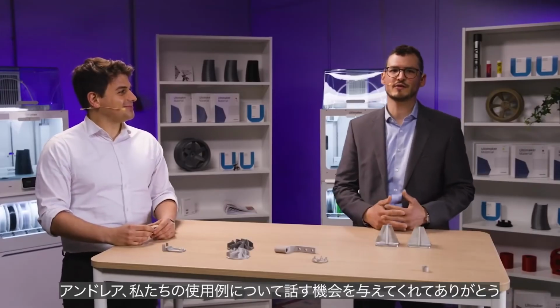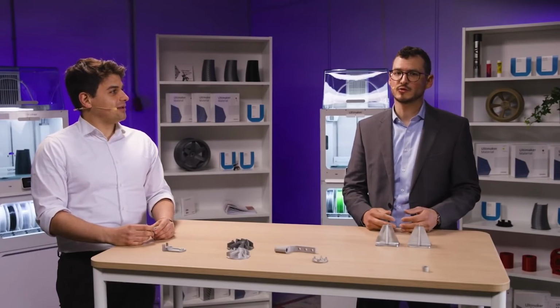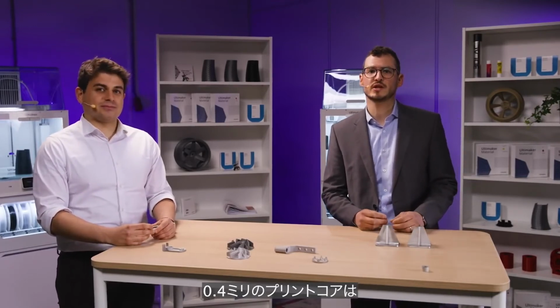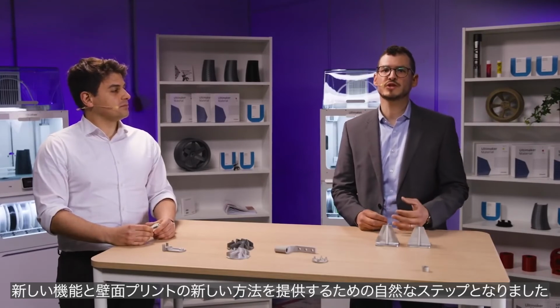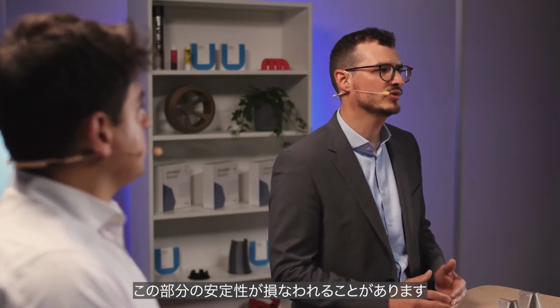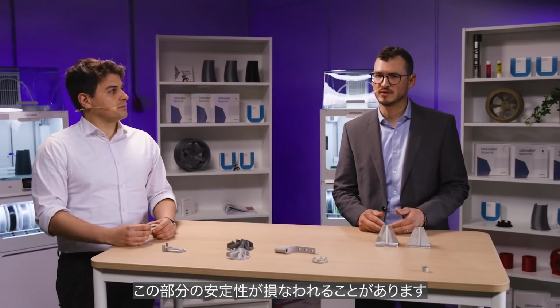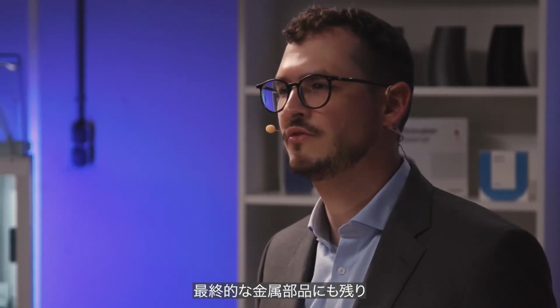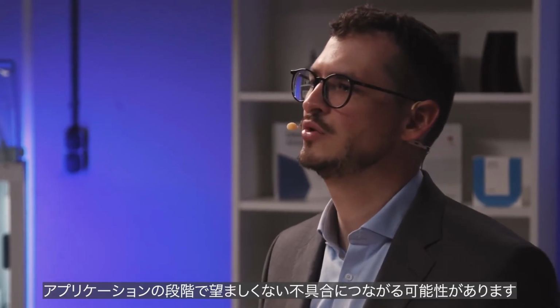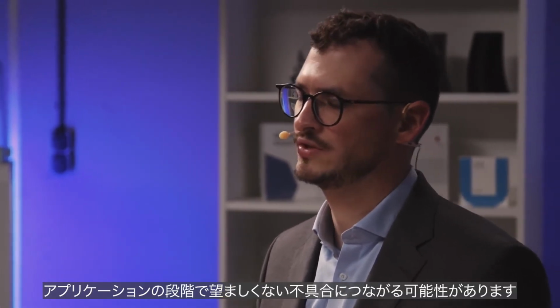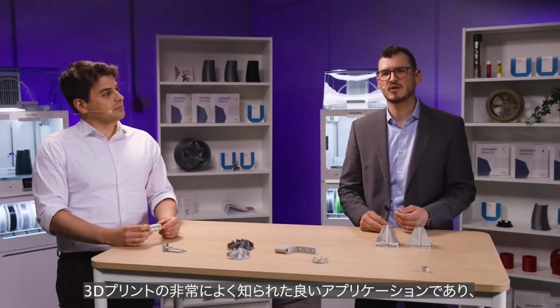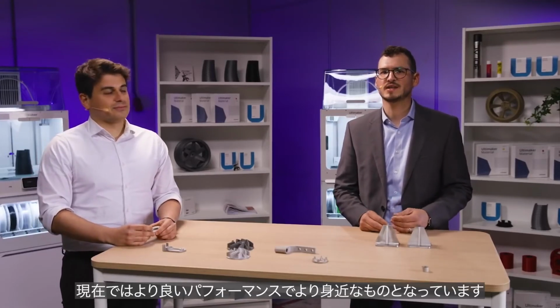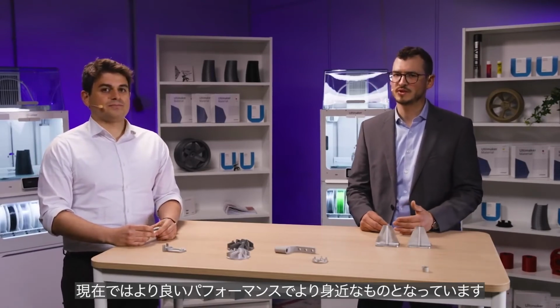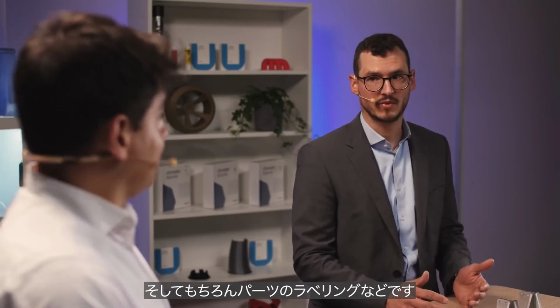Thank you, Andrea, for giving me the opportunity to talk about our use cases. So with the new CC 0.4mm print core, for us it was a natural step for new features and a new way to print thin walls. Thin features can suffer from voids and small gaps, which reduces the stability and integrity of the specific area. Not only in the debinding and sintering process, also in the final metal part, these defects would still be there and could lead to an undesired failure during the application. So printing small details is a very well-known and good application for 3D printing and is now more accessible with better performance. For example, vertical or horizontal holes and of course labeling of parts.